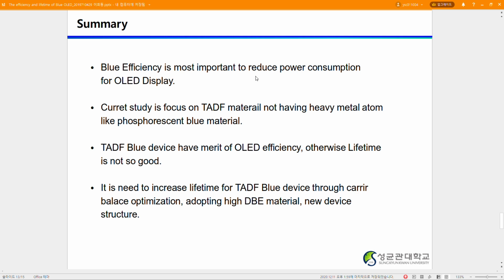The material development strategy suggested above should be combined with a device strategy to suppress degradation processes such as triplet-triplet annihilation TTA and triplet-polaron annihilation TPA. For example, a graded doping structure, stepwise doping structure, interface exciplex structure, and host exciton managing structure can be employed for further extension of the lifetime of the TADF host-based phosphorescence OLED and TADF OLED.